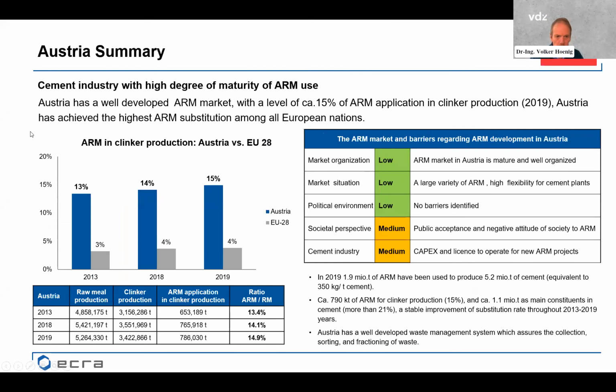Summary for Austria. From the market point of view, we can say that Austria has a really well-developed alternative raw materials market, which allows this really high level of 15% substitution rate in raw materials. By this, Austria is number one in Europe. You see here again this positive trend, which I've mentioned already before. In 2013, the level was 13%, and in the meantime, it came up to 15%.